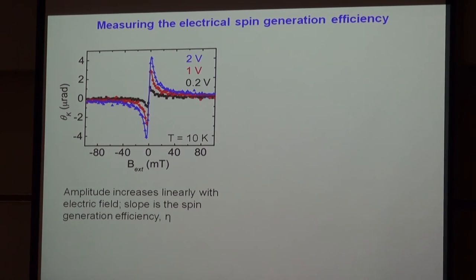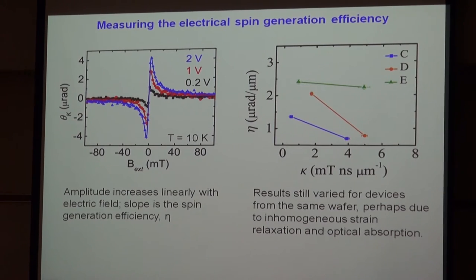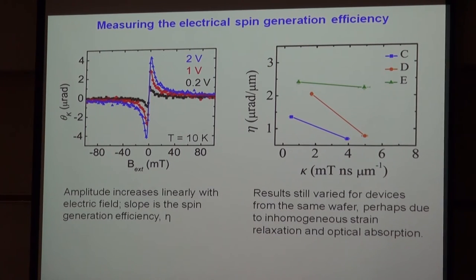We set up these measurements in our lab and started measuring a few different devices. We were frustrated because these are all results from the same wafer, so we thought we should normally get the same result, but it still seemed to vary. Our hypotheses are that there could be some inhomogeneous strain relaxation across the wafer — we made these samples strained to increase the spin-orbit field — but maybe the strain, optical absorption, or composition is not uniform. We even tried making a map and looking at how this varied, but there wasn't a clear trend.